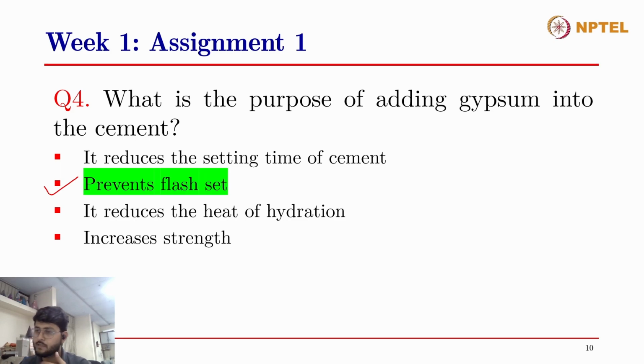These C3A molecules dissolve in the pore solution and react very fast with the water to produce what we call hydrogarnets. This happens when there is no gypsum. These crystalline hydrogarnets are formed when C3A reacts with water in the absence of gypsum. As they are crystalline in structure and have a large volume, they set the cement or concrete very quickly, and that leads to the flash set. It reduces the workable time, the open time that we have with the cement or concrete.